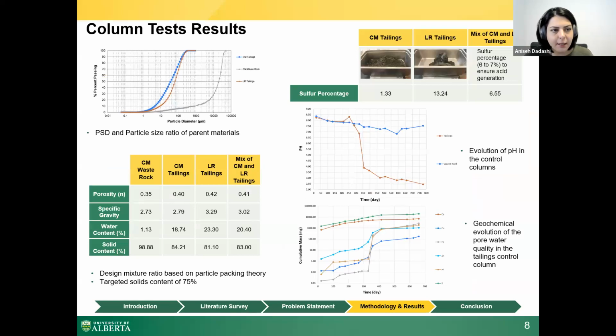Here you can see the particle size distribution and basic physical properties of the parent material. As I said before, the porosity and specific gravity were used to calculate the ideal mixture ratio. Tailings were consolidated during transportation and storage, so our solid content was very high. We added water to keep the solid content at 75%, which replicates the paste tailings.